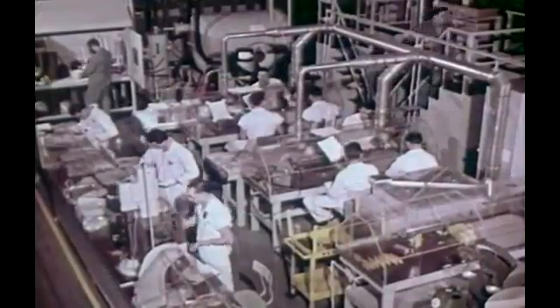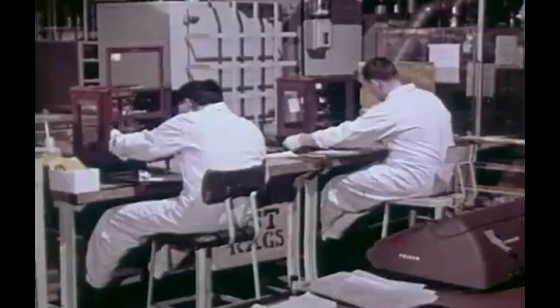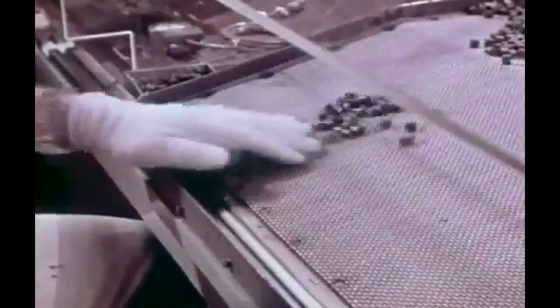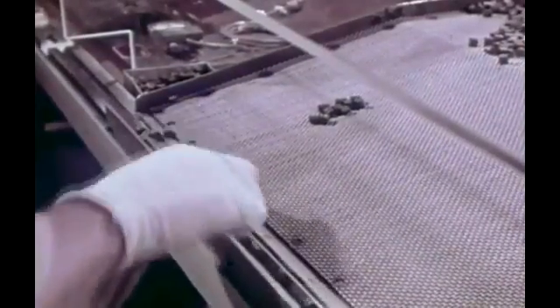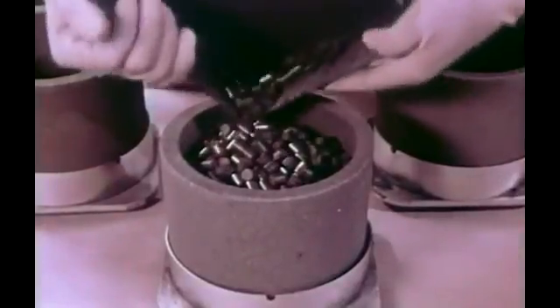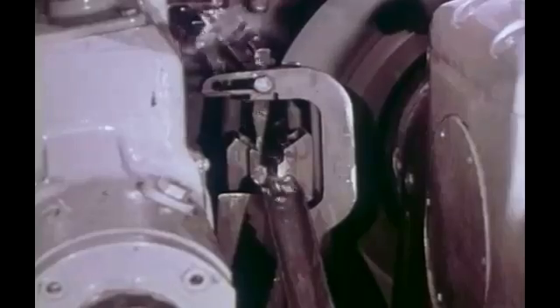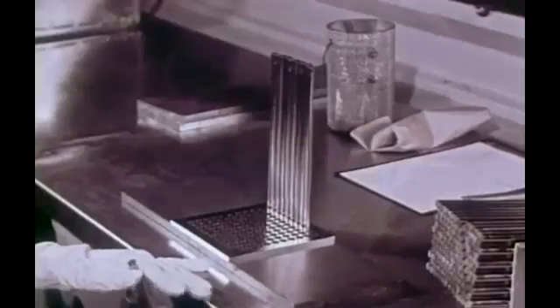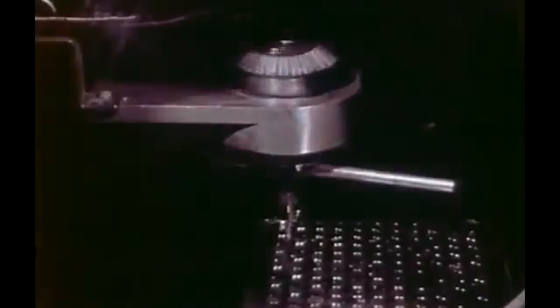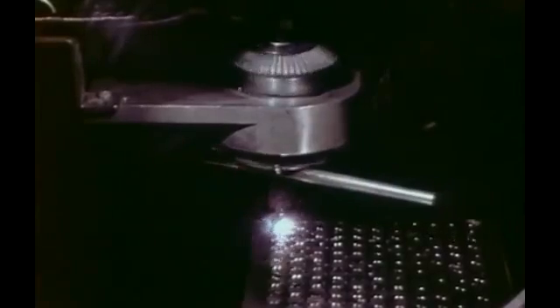Although the development of the manufacturing processes was then begun, the extensive test program was continued to verify the selection of UO2. More than 2 million uranium oxide pellets and 95,000 blanket tubes were made. Processing of pellets included agglomerating, compacting, sintering, and grinding. Fuel rods and bundles were assembled, argon atmosphere welded, annealed, and machined.